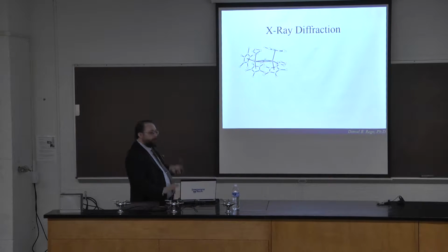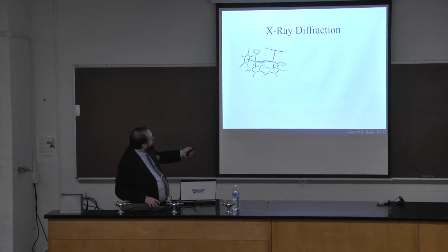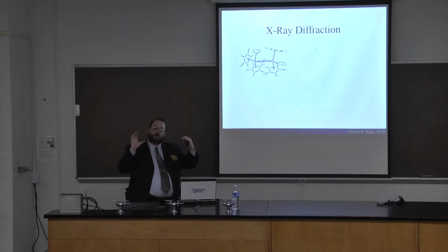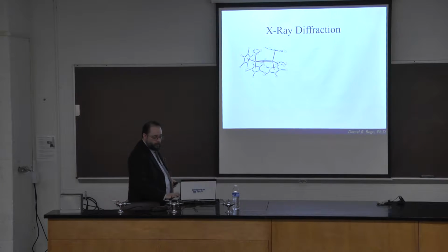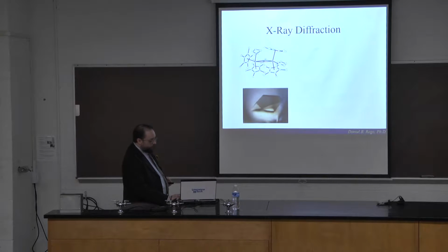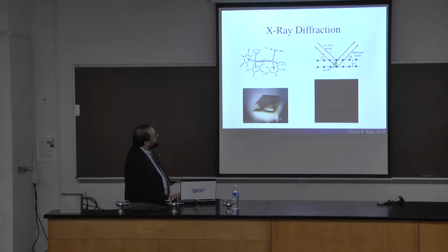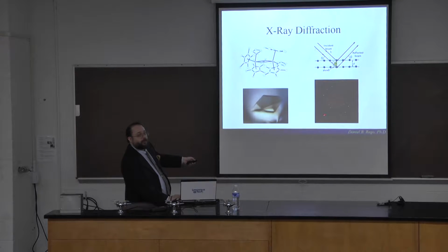Now with X-ray diffraction, basically you have a certain compound. This is a cerium dinitrogen compound. And you have a bunch of these in the same configuration, all stacked together in the same orientation, just similar blocks all stacked together. And it forms beautiful crystals. And what you can do, because these are all stacked together in the same way, is diffract X-rays through the crystal, and you end up getting these patterns and concentrations of the diffraction into certain diffraction patterns. And if you take a lot of these patterns from a lot of different angles of the crystal, you can actually back calculate what the structure is. And this structure is actually determined from a bunch of pictures like this.